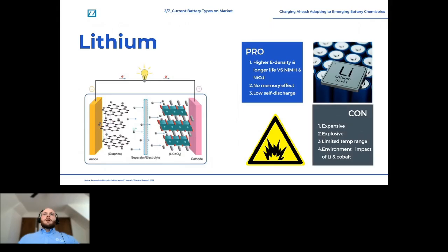Some downsides to lithium ion are that it includes thermal runaway issues due to the lithium dendrites, which can form during charging on the anode. And if they are able to reach the cathode, this creates a short circuit, which leads to thermal runaway and explosions. They also have a higher cost and recycling challenges. Furthermore, sourcing materials like lithium, cobalt, and nickel can be a challenge.